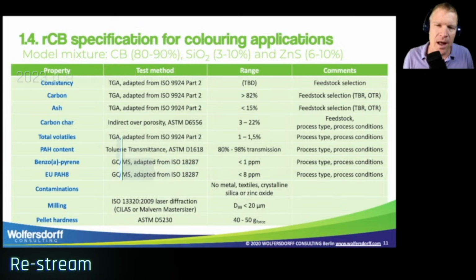At first, it is important to know, and this also comes on the safety data sheets, the model mixture of recovered carbon black is carbon black, silica, and zinc sulfide. So the carbon black can be anything between 80 and 90%. This is feedstock dependent, as we discussed before. It can be 3 to 10% silica, or even slightly higher than 10% if we have a very high silica content feedstock. Zinc sulfide could be 6 to 10%, for example.